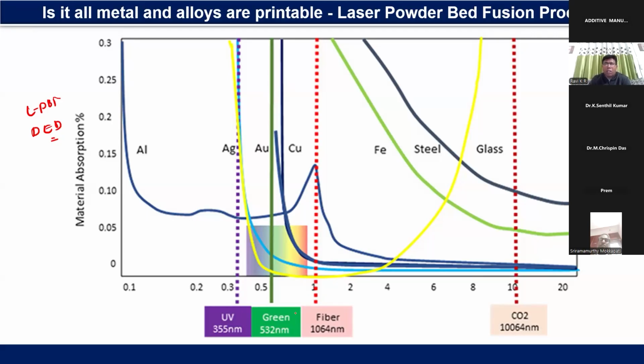We usually use the laser somewhere in this region, 1064 nanometer. It can vary from 950 to 1064 nanometer. All the materials have different types of absorption. The material should absorb. If the material absorbs, only then can it melt the powder. If the material reflects, you cannot melt the powder.